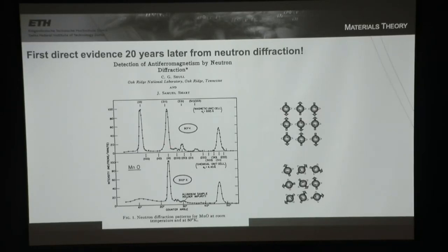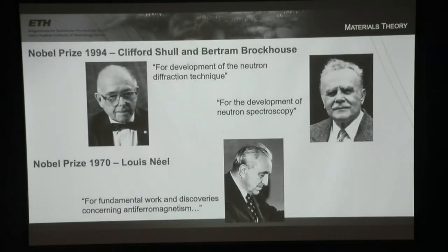Of course, we still have the crystallographic peaks, but now there are additional peaks associated with the additional magnetic order, the additional symmetry lowering. And if one analyzes the details of which peaks are there, one can extract precisely what the magnetic order is. So I would say that after the 1950s, when we had neutron diffraction, antiferromagnetic order was no longer a hidden order. It could be really measured directly and quantified. And this was very important.